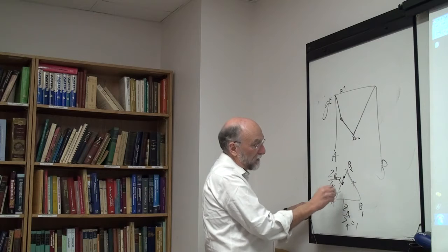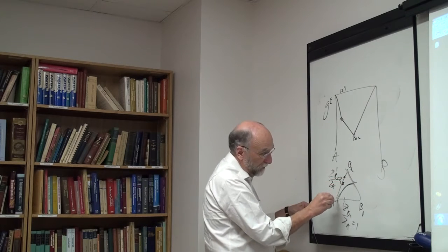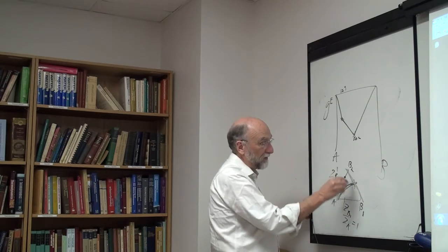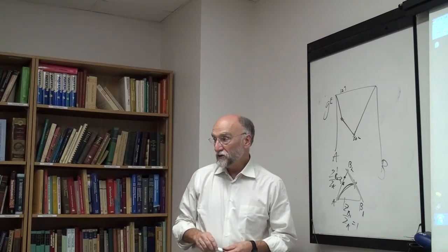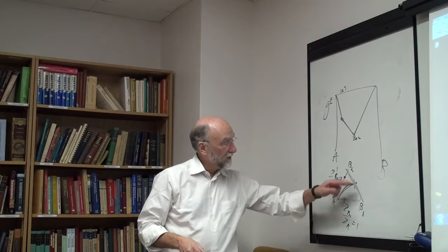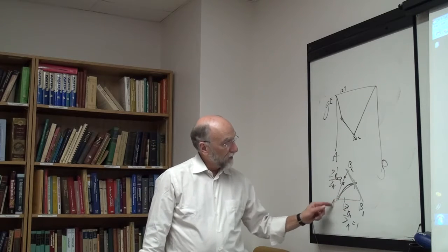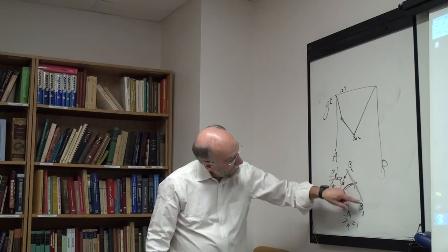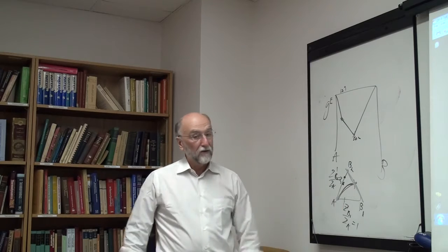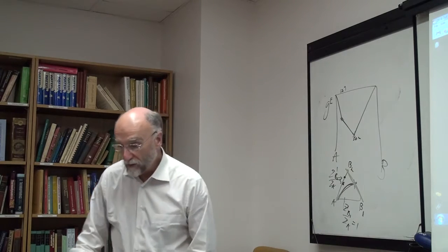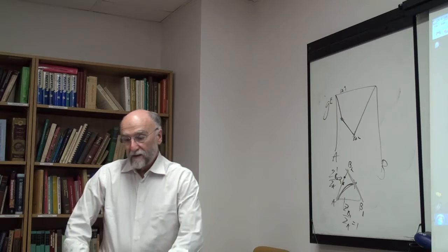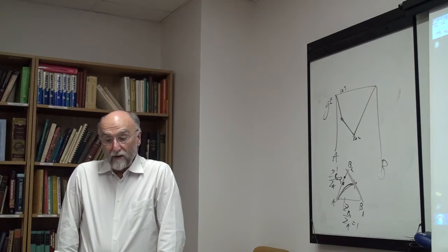And then it means that pure B is somewhere, the actual system goes along here, so in pure B you actually have a mixture of the two coordinations and so on. So you actually treat it as a ternary system, A, B1, and B2 with the quasi-chemical model, and then pure B is some mixture of B1 and B2 depending on their relative G0, so you don't have to worry about that. We've used that in the sodium fluoride, aluminum fluoride in model cryolite.